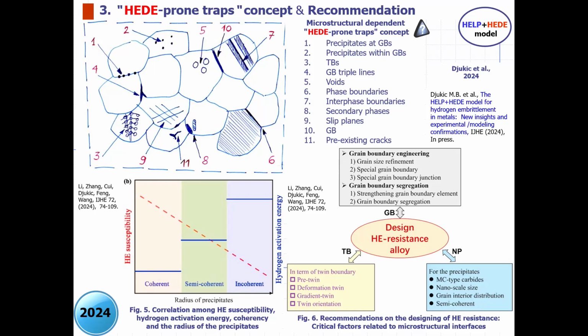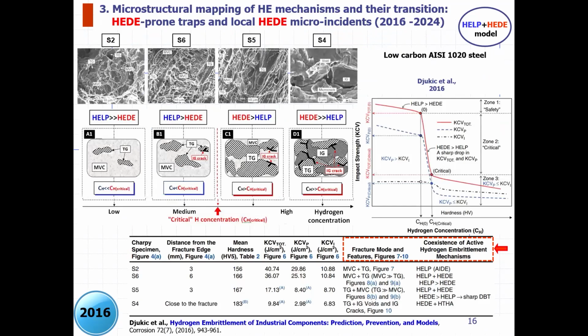So we proposed in our recent paper from 2024 with Chinese authors a design of a hydrogen embrittlement resistant alloy based on careful engineering of twin boundaries, precipitates, and grain boundaries in the metallurgical design, in order to provide that the precipitates are particularly good ones, semi-coherent with the matrix. So we must carefully, and on the other slide we will see how the high-strength high entropy alloys with precipitation hardening are very prone to hydrogen embrittlement because this scheme was not involved during the design of that particular alloy.